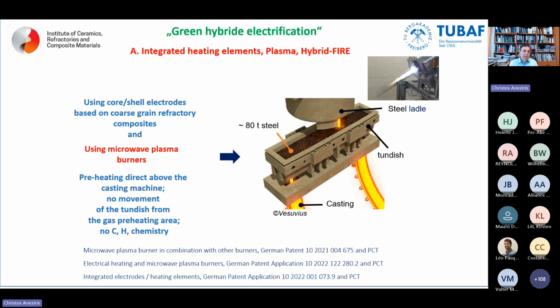And somebody would say, can this technology, that means the high temperature electrification, also be applied in conventional traditional vessels in the metallurgy, like in a tundish vessel? Normally, in this kind of vessel, 80 or up to 90 tons of steel as a buffer are applied in continuous steel casting. They are preheated with natural gas burners, so you have the CH chemistry which interacts with steel, not in a positive way. So what would be if we have integrated core/shell electrodes and use additionally also microwave plasma burners? Less thermal shock, less corrosion, and at the end of the day, a higher durability of the whole system.